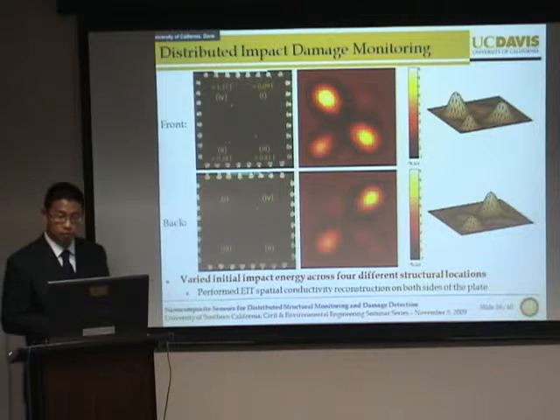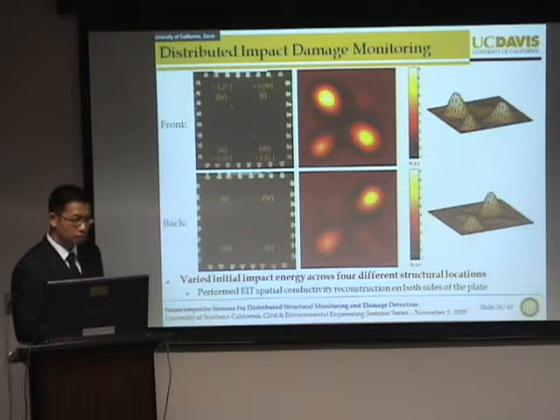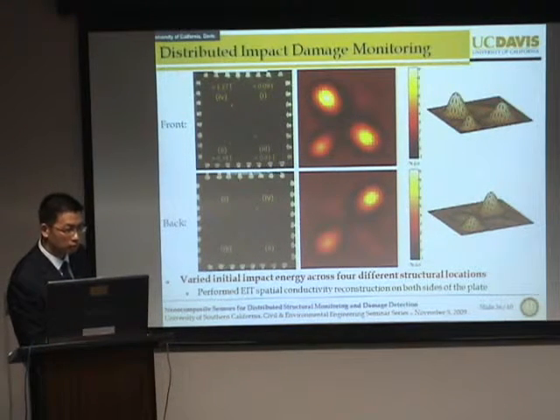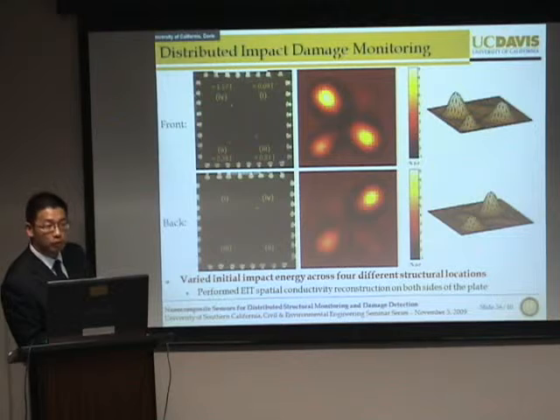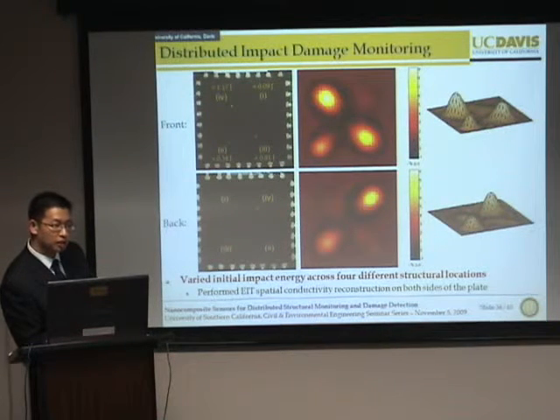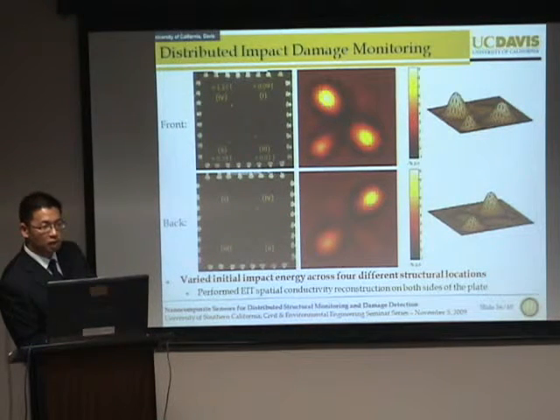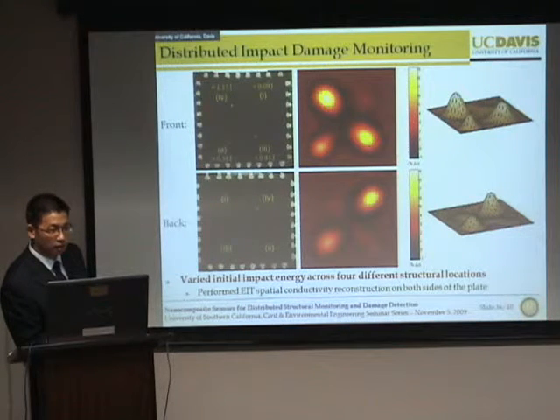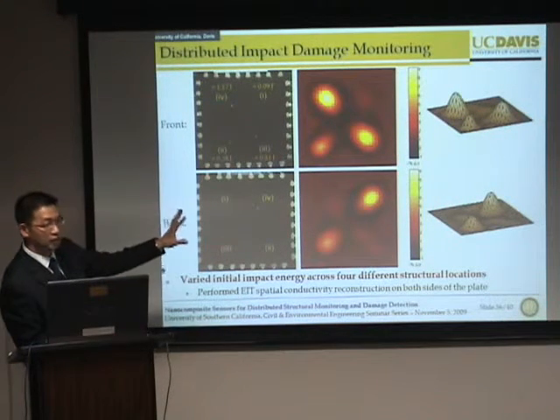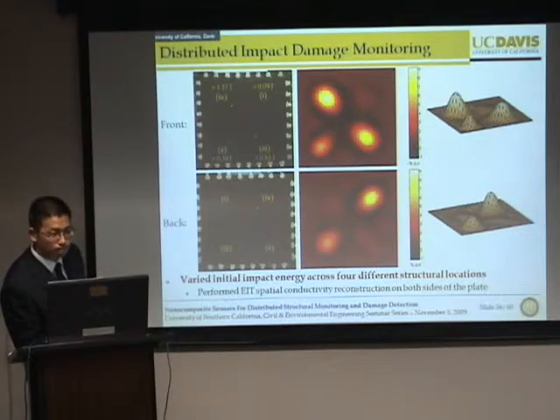So I'm sorry, the change in conductivity is due to a pre-existing condition in the plate or to damage induced by the hammer? The change in conductivity is due to the thin film that we deposit onto it, but the change in conductivity of the material is caused by permanent deformation of the plate. Pre-existing? Due to impact. Right, right. So initially, if we look at just the conductivity map, it's just uniform.